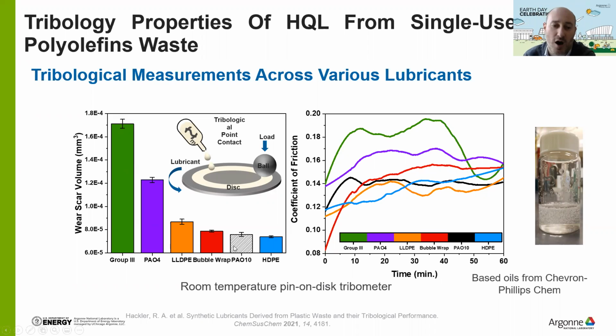All the oil from the linear low density polyethylene and high density polyethylene have very, very interesting properties that resemble the polyalpha olefin, both on the wear scar on the left and on the coefficient of friction. And we also add to this testing bubble wrap. Bubble wrap is a very interesting material, and if you visit one of the MRFs, the material recycling facilities, they